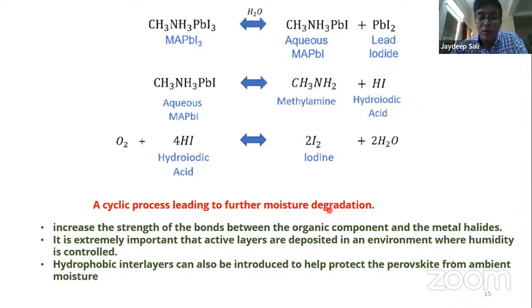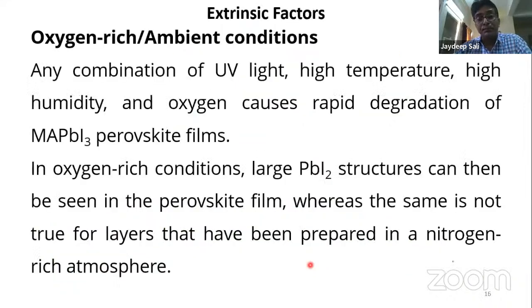So we have to have a controlled humidity environment for manufacturing of the thin films, and hydrophobic interlayers can be introduced in between certain layers. We can introduce hydrophobic interlayers which will protect the perovskite from ambient moisture. Okay, now the second possible cause of degradation of the perovskite is oxygen-rich environment.